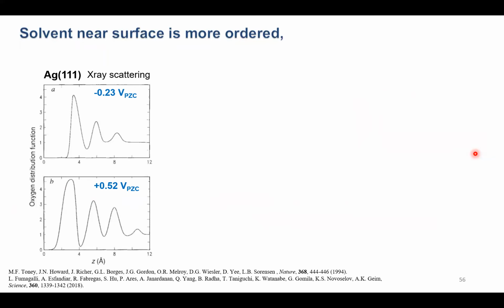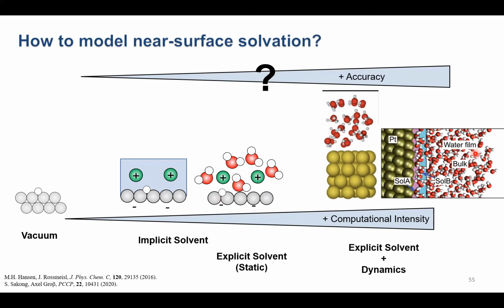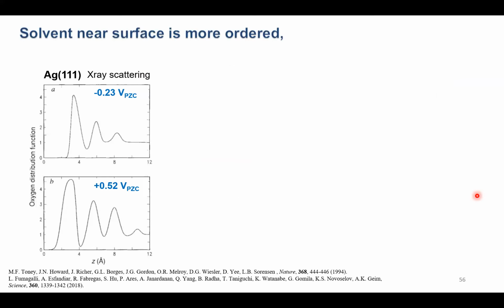The last comment I want to make is just the behavior of water. We should keep in mind the behavior of water near an electrode surface is very different than it is for bulk water, right? For bulk water, we imagine lots of water molecules all moving around at 300 Kelvin. We can form these long time scale, long length scale, hydrogen bonded structures. But in the electrochemical environment, water near a surface tends to be far more ordered than bulk water.